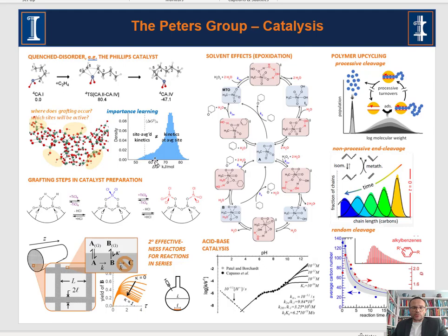And to give you an idea how this is different from typical machine learning calculations and how it's different from typical catalysis applications, this is a distribution of activation energies on the different sites that are present. The only ones that are going to actually do anything are these ones out here on the left hand into the tail. And so what ends up happening is that the site averaged kinetics are very different from the kinetics of an average site. And so we're wanting to quantify that so that we can figure out what are the characteristics of that 1% of sites that are actually doing all the catalysis, and could we make a catalyst that had more of them or was entirely like them.